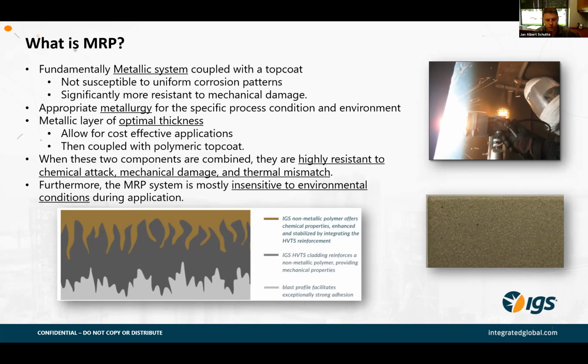There's a picture at the bottom here that shows the light gray is your substrate, which, for instance, would be carbon steel. Then you've got a blast profile, which facilitates very strong adhesion for the HVTS cladding. The cladding itself creates a metallic layer for the non-metallic polymer and provides an excellent reinforcement media for that polymer to grab onto. That polymer in itself gives you a range of chemical properties to give you further protection. So really the best of both worlds from both technologies.